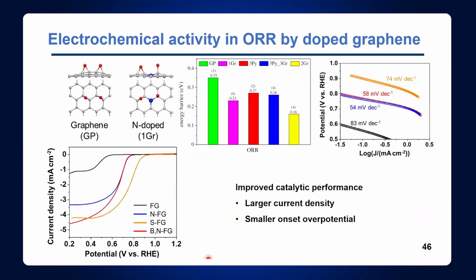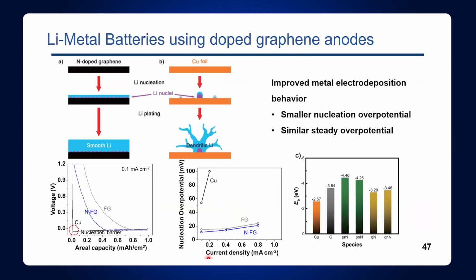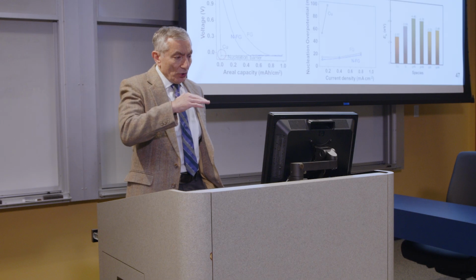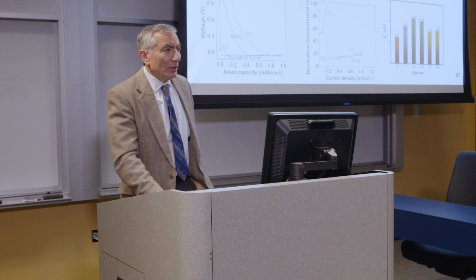And then we used it as a catalyst, because the graphene itself can be a catalyst, but if you have heteroatoms there, the catalytic behavior can really go up. And so we use this for an oxygen reduction reaction, taking oxygen and reducing it. We used it in batteries. So again, we've used these films, and we grow the lithium on top of this for a lithium metal battery. We grow it on this, and it is better than just growing it on graphene, because these little heteroatom sites serve as an anchor for keeping the lithium on there.